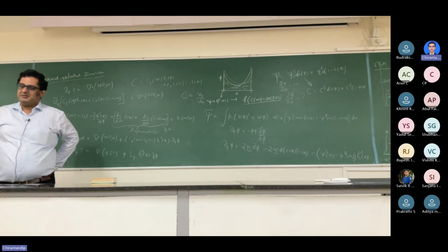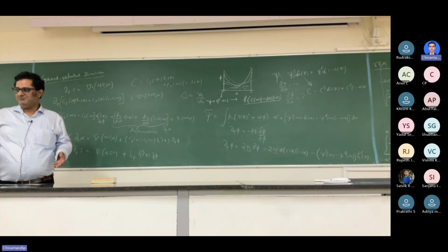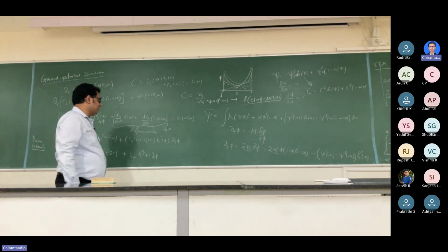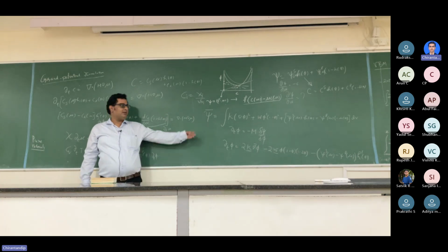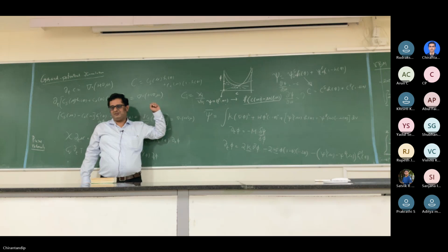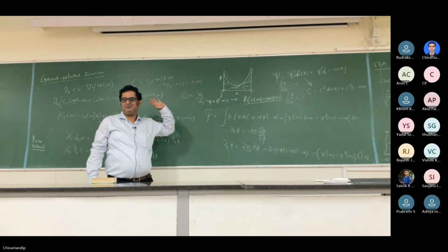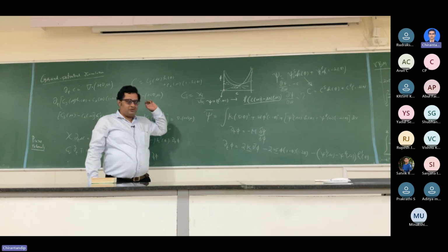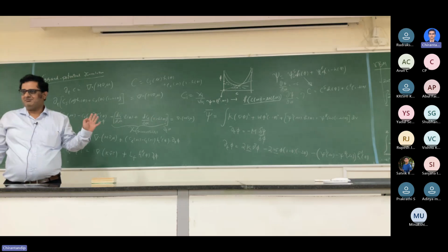If you do not make that assumption, you will naturally have liquid flow when systems move, or there will be stress in your material when diffusion happens. But since you don't consider either of them, the actual assumption is that the molar volumes of the species are all the same. And if the molar volumes of the species are all the same, this is just a scalar conversion. All you did was a reformulation of the problem.